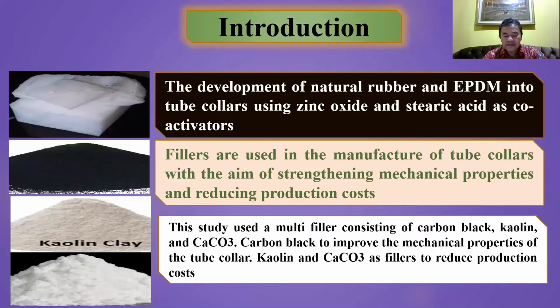The development of natural rubber and EPDM into collar uses zinc oxide activator and stearic acid as co-activator. Fillers are used in this manufacture of tube collar with the aim of strengthening mechanical properties and reducing production costs. The study used a multi-filler consisting of carbon black, kaolin, and calcium carbonate. Carbon black improves the mechanical properties of the tube collar, while kaolin and calcium carbonate are fillers to reduce production costs.